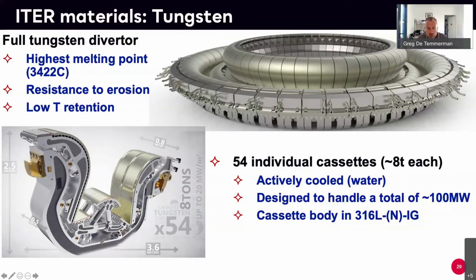And the body of it, on which it is fixed, is made of stainless steel. It's a special variant of 316L because we need low nitrogen content, because nitrogen tends to activate. And what you might notice is that the divertor is made of very small blocks again, and you have about 250,000 of those blocks. Typically, they are 2 centimeters by 2 centimeters by 12 millimeters. So these are very small pieces.